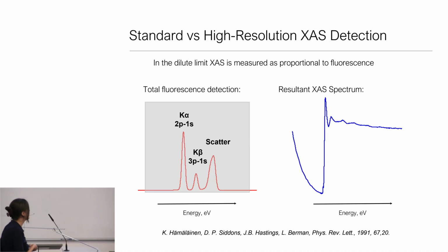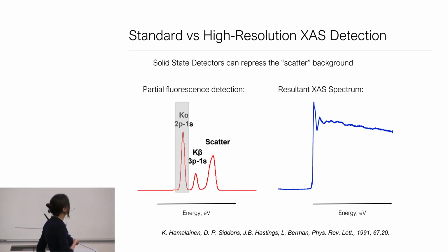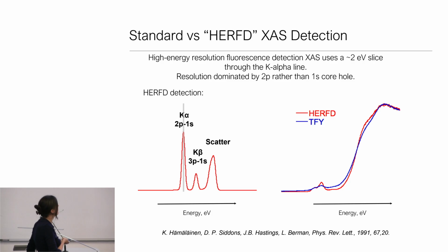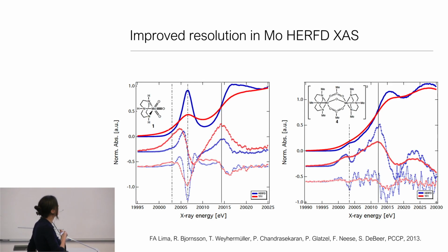But one of the ways that my group, and I think many other groups, use this most often is to get high energy resolution detected absorption spectroscopy. And so this is basically where, instead of taking that wide electronic window that I talked about that just reduces background scatter, we can take a very narrow window around the 2p, and what we start to see is spectral sharpening. And one of the biggest problems with X-ray absorption spectroscopy is the core hole lifetime broadening, especially for heavier elements. And what happens with these kinds of detection methods is, if you look at the HERFD detection, which is shown in blue, you start to get much sharper features.